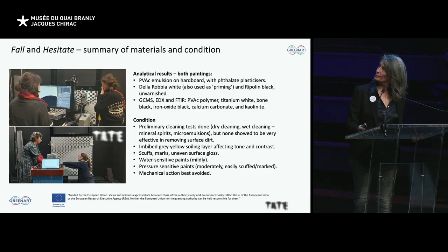In terms of condition, we did some preliminary cleaning tests, and we didn't get much on the swabs, but we knew there was an ingrained surface dirt layer on both of these works. And the soiling, certainly at Tate, seems to be kind of grey-yellow, quite tenacious soil, especially for works that are fairly constantly on display. And these works were the same as the other works we've cleaned. Water-sensitive paints, because they're polyvinyl acetate, and I think the biggest risk was they're pressure-sensitive, so any kind of pressure on the surface causes the gloss to change quite markedly.